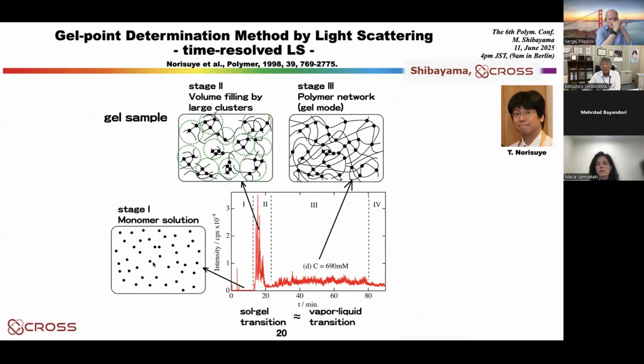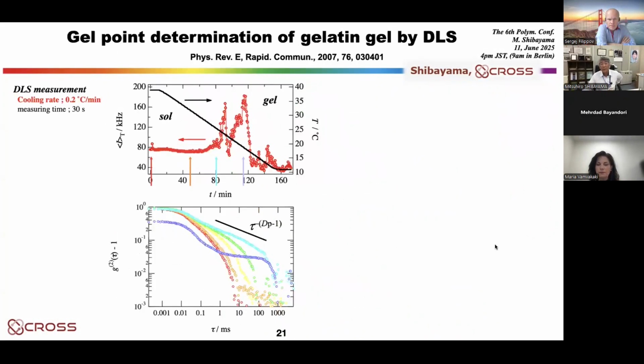At the beginning, the particle is so small it doesn't scatter so much, but here the polymer chain grows and grows and occupies the whole space. So this is why the scattering is very big. This is why the strong scattering. However, from here to here, it is now condensed matter. It's a continuum. This is why there's no envelope. So this is why the scattering intensity decreases. This is analogous to the vapor-liquid transition. You see the critical opalescence of the gases. This is the same case.